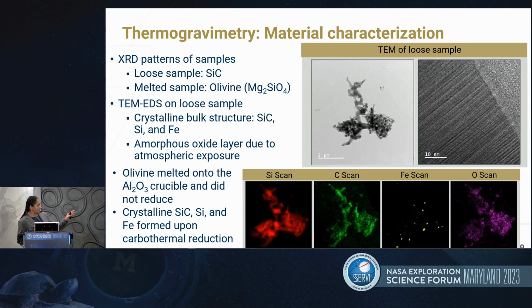So as you can see, small sections of the silicon scan did not coincide with the carbon scan, and the iron scan did not coincide with either. And it's expected the amorphous layer was an oxide layer, as shown by the oxygen scan.